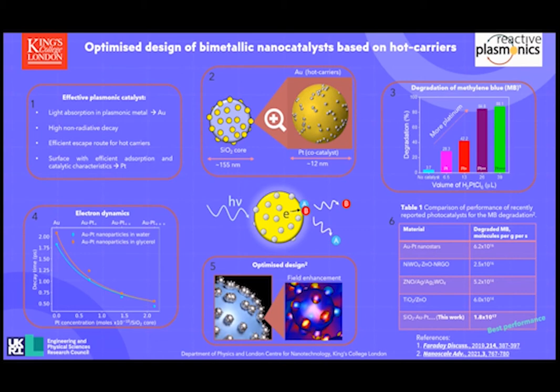At these nanoclusters, field enhancement is substantial, and they become hotspots for efficient hot electron generation and extraction. At these spots, it is more likely that a hot electron would be extracted. These nanoclusters are crucial for the enhanced performance. The optimal design consists of 12 nanometer gold nanoparticles and 3 nanometer platinum nanoclusters.